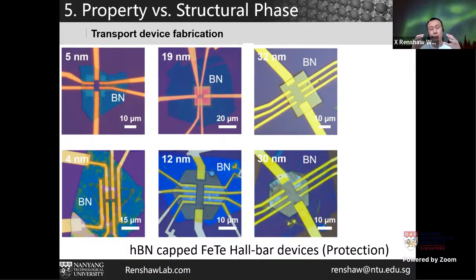Because for using the transport properties, for example, here we fabricate a series of 2D devices. We have the flake, we put the hBN on top of the devices, and we just measure the magnetic properties by passing the current or detecting the voltages. When we measure the magnetization, we are measuring the whole sample, including the flakes and a big substrate. While here, if you measure the transport or the electrical properties, current only passes through the sample. So whatever we pick up is only from the device.